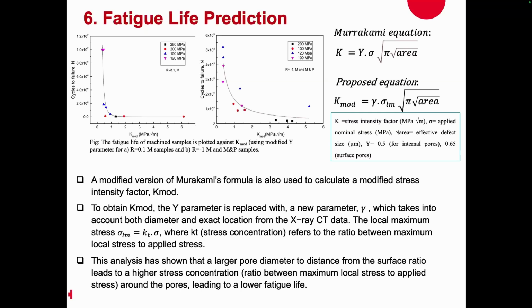We use the CT data and local maximum stress, Kt times sigma, which we can use in this formula, and it can also accommodate a large pore diameter, and it uses a ratio, which is the pore diameter to distance from the surface, and which leads to higher stress concentration. So basically, the ratio between the local stress to applied stress around the pore leads to a lower fatigue life. So this formula, although it's empirical, it's very crude, tries to incorporate some of the phenomena we observed, which is the size of the pore, proximity of the pore to the surface, and how we can take into account with a modified factor K mod in our equation.